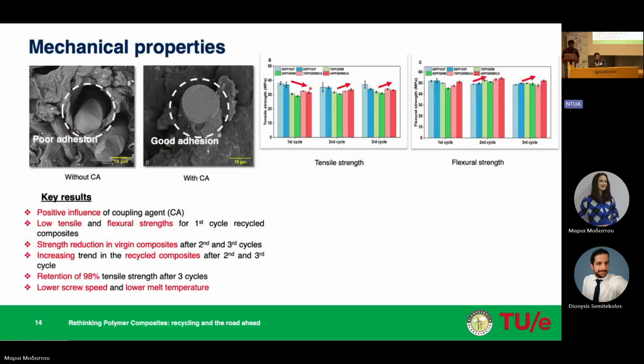And later on, obviously it was needed to understand the mechanical properties of these composites. In order to have a better adhesion between the fiber and matrix, as I said, we also used a coupling agent called maleic anhydride grafted polypropylene, which helped to enhance the adhesion between the fiber and the matrix. As you can see here, this is the picture of the polypropylene composite before adding the MAPP coupling agent. You can clearly see the poor adhesion between the fiber and the matrix. And after using the MAPP coupling agent, it was indeed helpful in achieving adhesion between the fiber and the matrix.